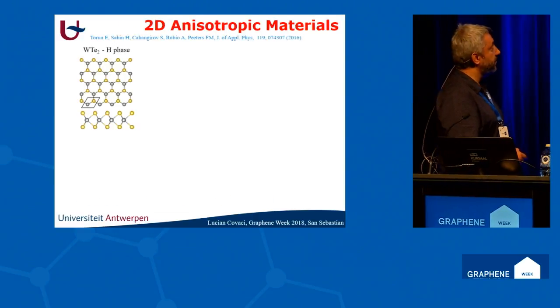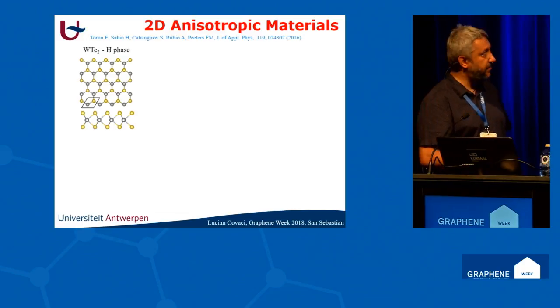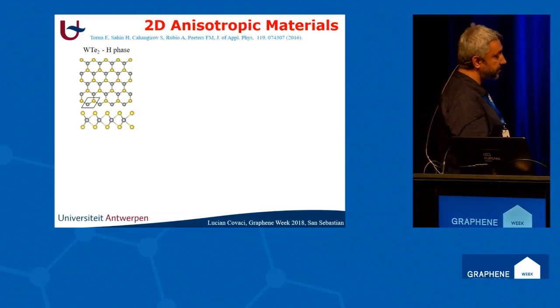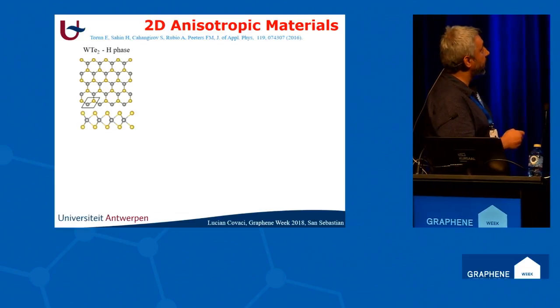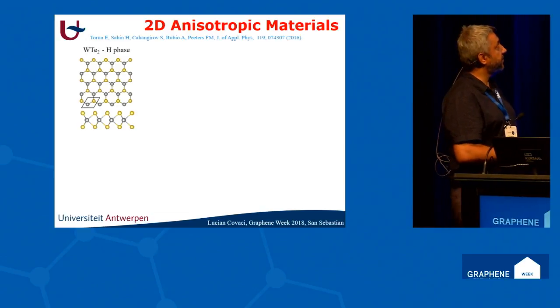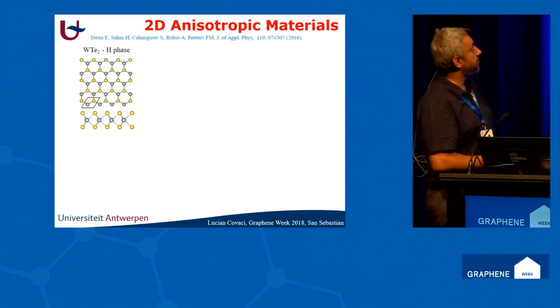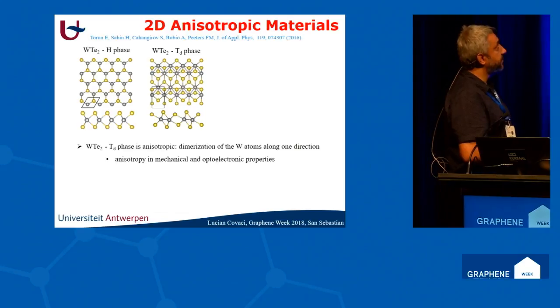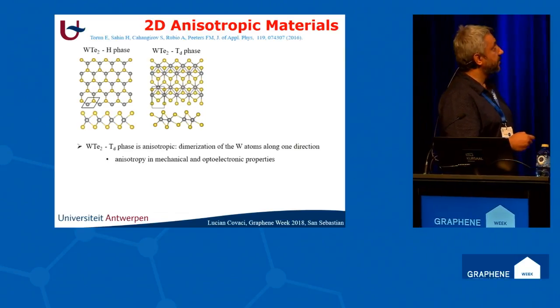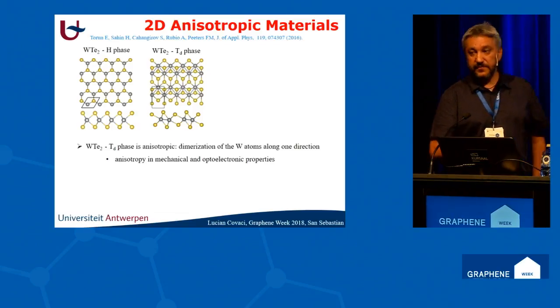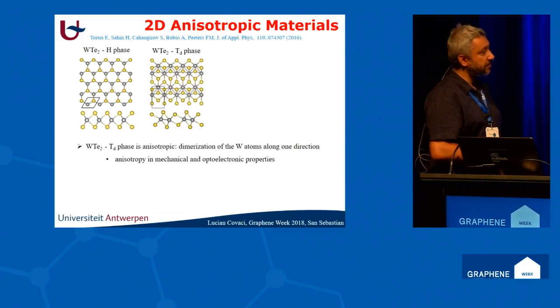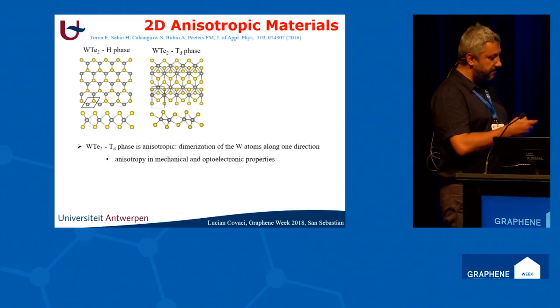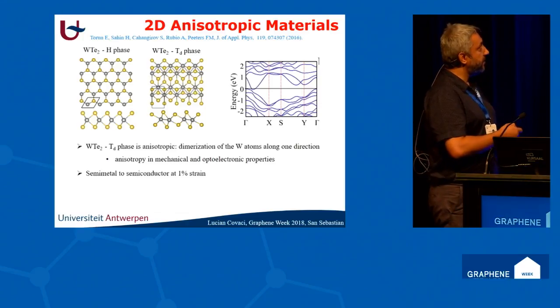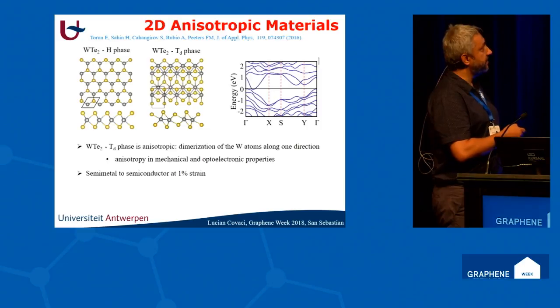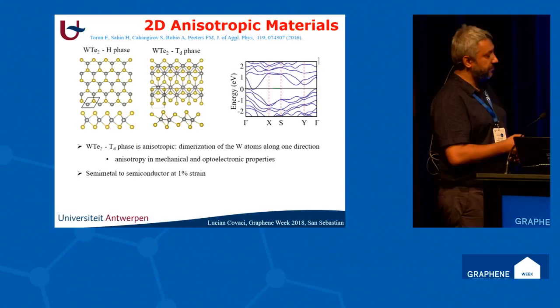So to just continue with some examples of types of calculations that we have done in our project. So first of all, we wanted to look at this interesting material, tungsten ditelluride, which of course is a two-dimensional transition metal dichalcogenide, but different from the usual ones which show the H phase and are semiconducting. This tungsten ditelluride has the lowest energy phase as a T phase, but it's a distorted phase. And because of the dimerization of the tungsten atoms, you have a very anisotropic situation, which shows up in mechanical and optoelectronic properties. So, for example, to start with, just the equilibrium configuration, so this material is semi-metallic, but it can be transformed into a semiconductor with just 1% strain.